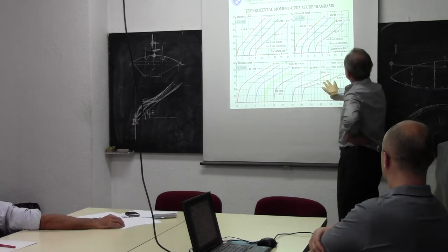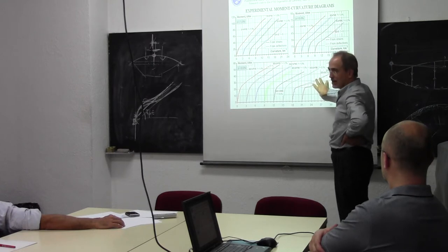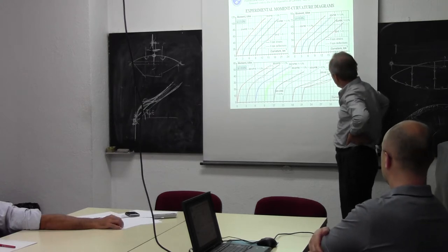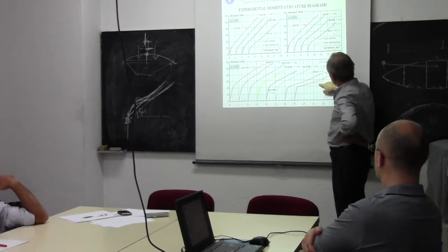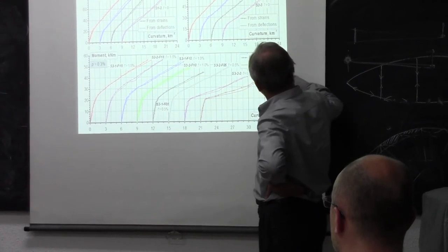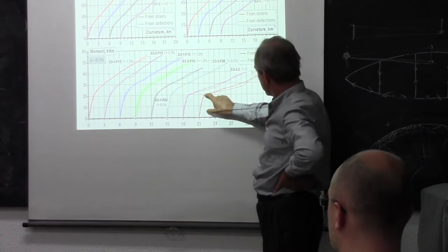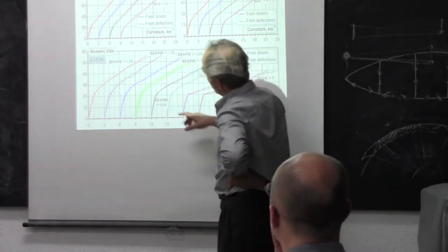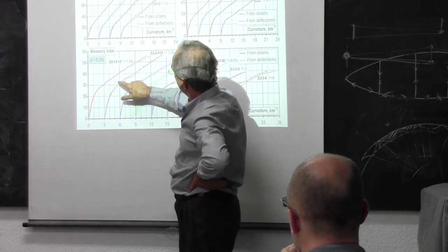Anyhow, here it is clear that I want to concentrate on this type of element, concrete without fibers. If you assume that the completely cracked stiffness will be a line more or less like this, you see that the tension stiffening is very important because the quantity of reinforcement is very small. And if you do that here, the tension stiffening is a little bit lower.